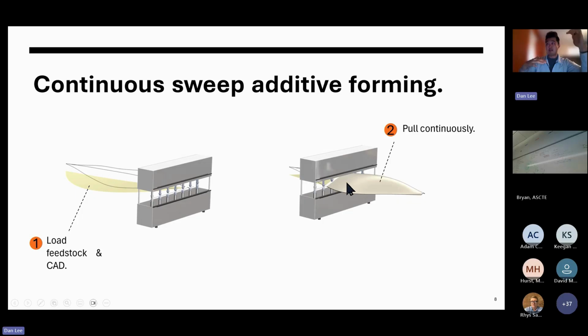And if you think about where that frontal polymerization is, where that interface between liquid and solid is, we control that very precisely in that machine. We do it in the plane of the die. So upstream of the die is completely liquid, uncured material, and downstream of the die is solidified material without a post cure. I wouldn't say it's easy. There are unique challenges with this type of process control, but it's been of great interest.